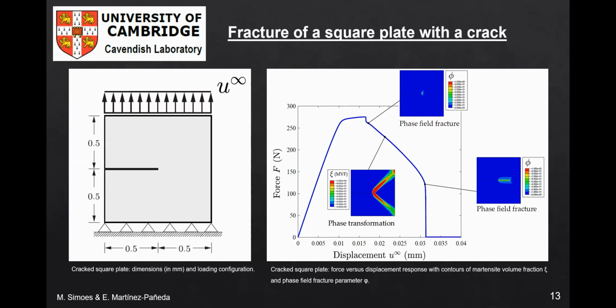We all know that in a linear elastic homogeneous material, the plate fails in an unstable manner, with the force versus displacement curve showing a very large drop immediately after reaching the peak load. However, in this case of shape memory alloys, a significant toughening effect is observed. There is an initial drop in the load associated with the first instance of crack growth, but then the crack progresses in a stable manner until complete failure of the sample. The toughening effect observed is related to the energy dissipated due to transformation.